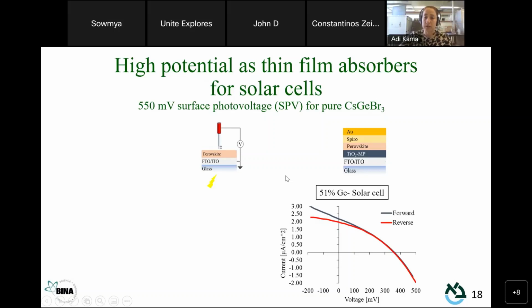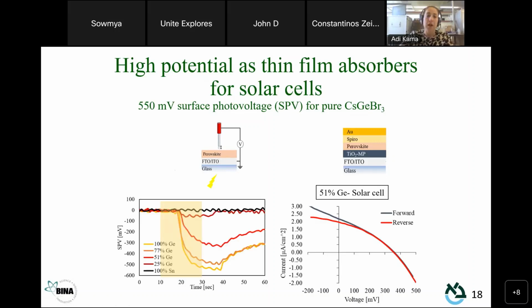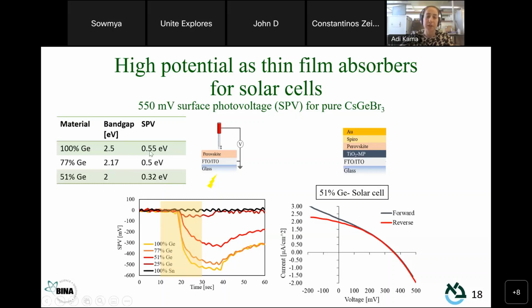So we tried to characterize it using surface photovoltage, which is a contactless measurement. We have a vibrating tip from a Kelvin probe. The stack is much smaller, so it's only half a cell, and we measure contact potential difference in the dark and in the light, and we see the photoactivity of this material. For the 100% germanium, we see a very good response with about 550 millivolts